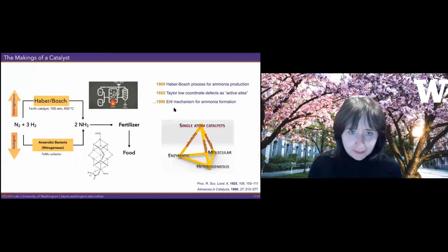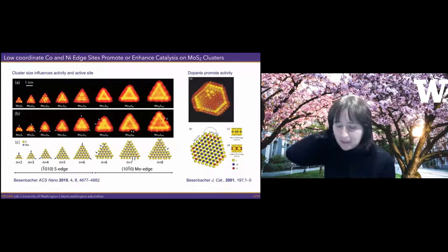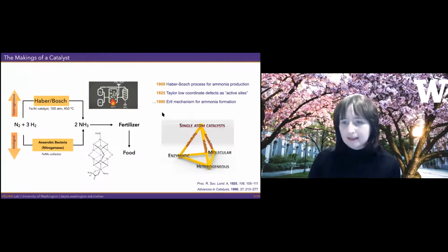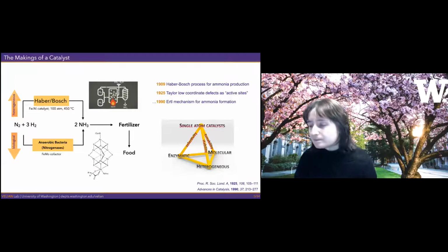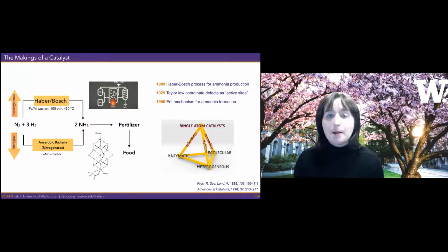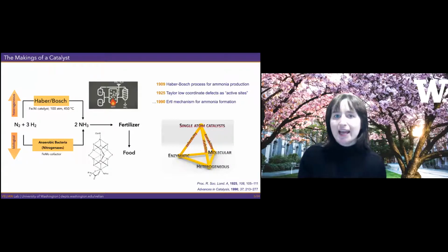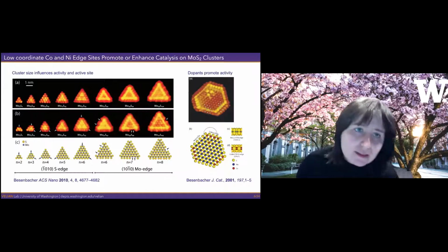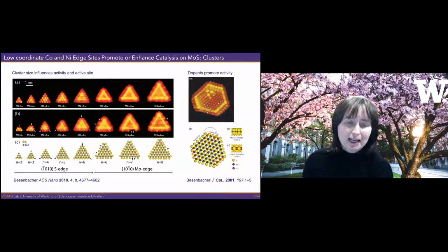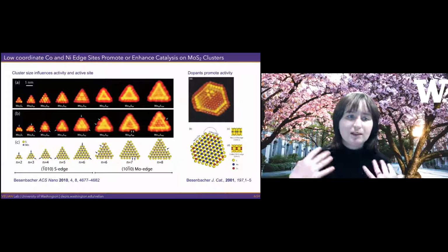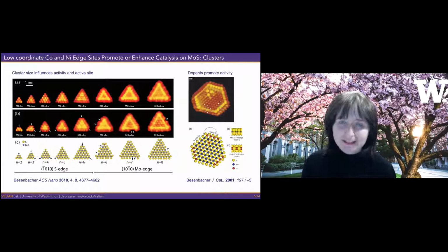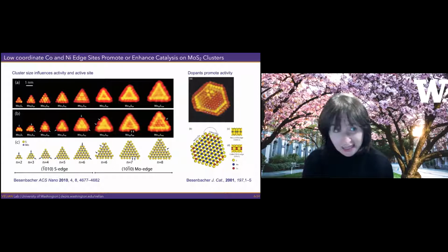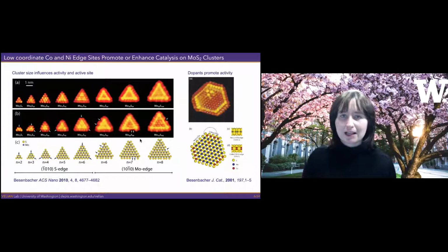So one of the interesting things about the presence of active sites is that the fact that they exist means that the size of the particle actually matters in terms of the activity of a catalyst and also its selectivity. And what I'm showing on this slide are two studies that I absolutely love because of how clearly they show exactly that point, how size affects reactivity as well as, as it turns out, selectivity. So molybdenum disulfide is a metal chalcogenide that has been known for a long time.